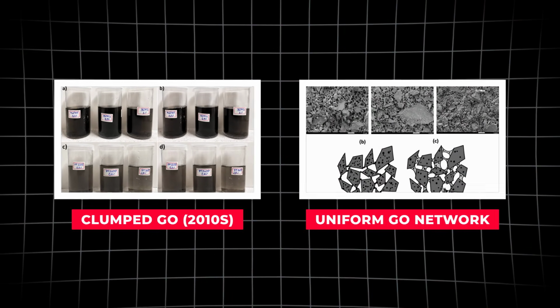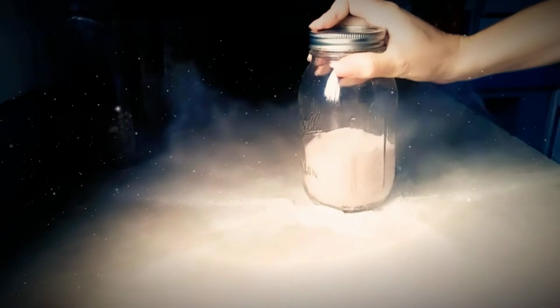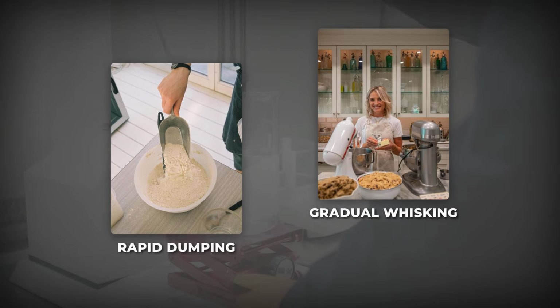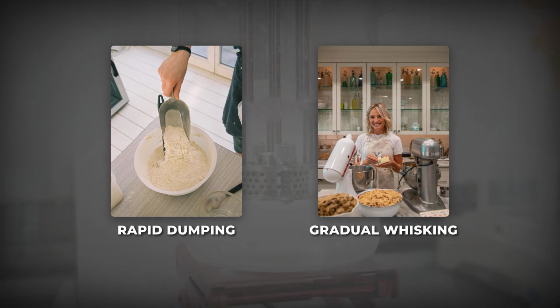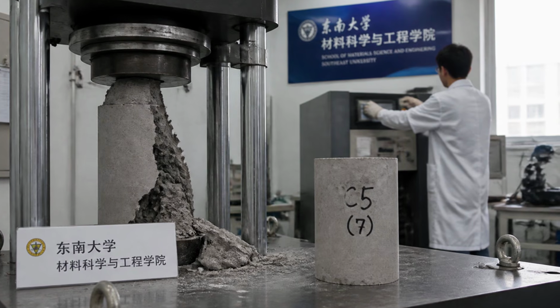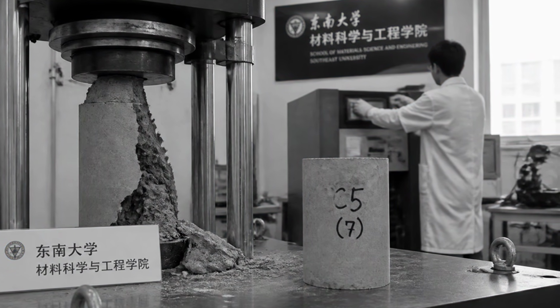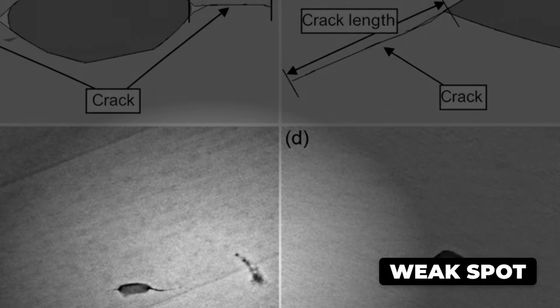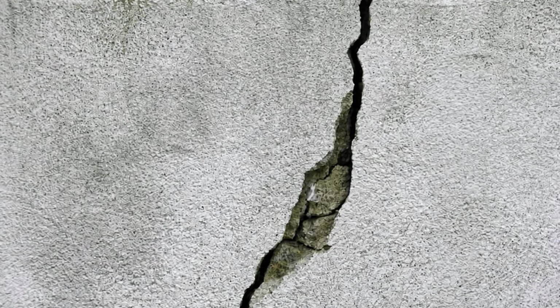Drop graphene oxide sheets into wet cement paste, and instead of spreading evenly through the mix, they clump together, the same way flour clumps into wet lumps in a bowl if you dump it into water, instead of whisking it in gradually. A clumped sheet of graphene oxide does nothing useful. Worse, it can create a fresh weak point exactly where engineers needed strength most.